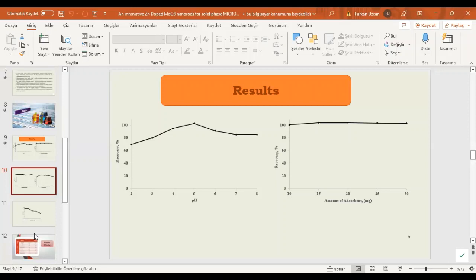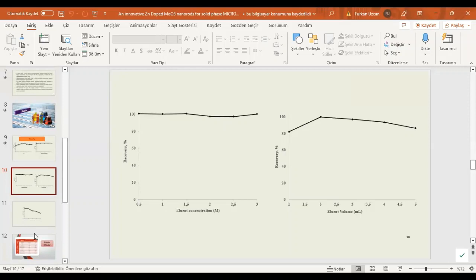Next figure is eluent concentration. We used nitric acid as an eluent between 0.5 molar to 3 molar. As you see, at all concentrations we used, we got quantitative recovery. So we use 0.5 molar nitric acid for the rest of the work. Next figure is eluent volume. After optimization of the concentration of nitric acid, we optimized eluent volume. We used 1 to 5 ml of 0.5 molar nitric acid. As you see on the figure, with 2 ml nitric acid we got quantitative recovery. So we chose 2 ml for further work.